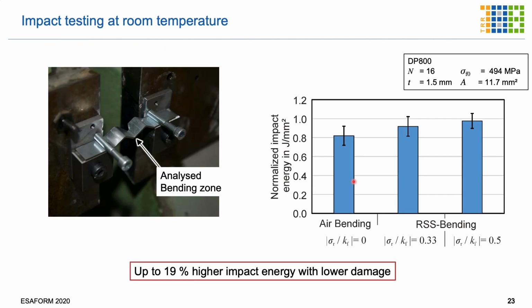And now, the next step, what is the performance of the part? For that purpose, we look at an impact energy test. So we use special specimens in this form. This is the bent area and this is the notch, and the impact test is conducted in this direction. What we found is that for a DP800 steel, we have an increase in the normalized impact energy with an increase of pressure. Here you see the approximate pressure values.